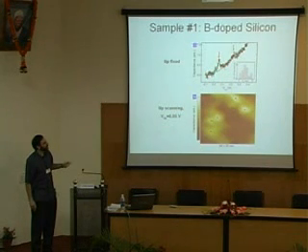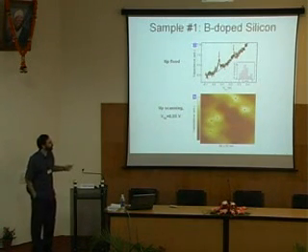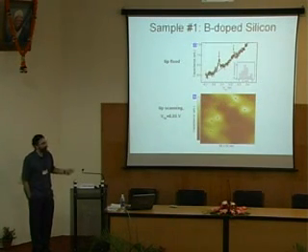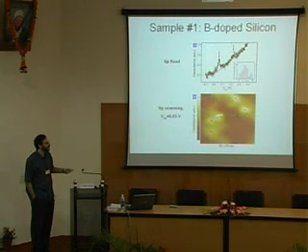This peak is more interesting to us, at least for this talk. That is the signal, we believe, of an electron going onto a dopant. So what I have below here is we parked the bias voltage of the tip right here at 0.05, 50 millivolts, and scanned the tip, moved it around the sample surface to see what happens to the capacitance. If the capacitance went up, then I plot a bright color. If the capacitance goes down, we plot a dark color. And fortunately, happily, what we see is a series of bright dots.